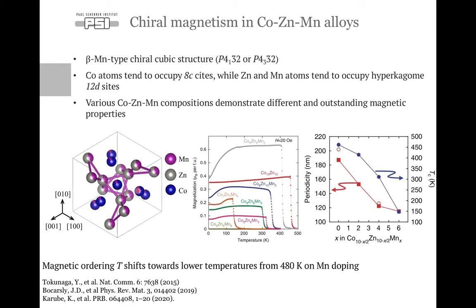The three-dimensional frustrated nature of this beta-manganese type structure gives us an opportunity to tune the magnetic properties of this family of alloys dramatically. For example, depending on manganese concentration, the magnetic ordering temperature, the transition from the paramagnetic state to the ground helimagnetic state, can be varied with manganese composition, and thus the TC can be pushed from around 480 K for the 10-10 compound up to 300 K in the cobalt 8, zinc 8, manganese 4 compound, just by doping this crystal structure with manganese.